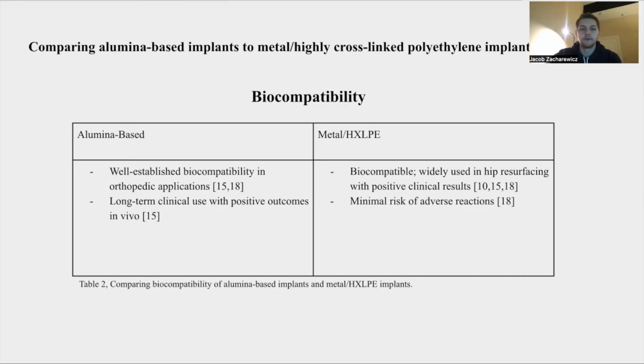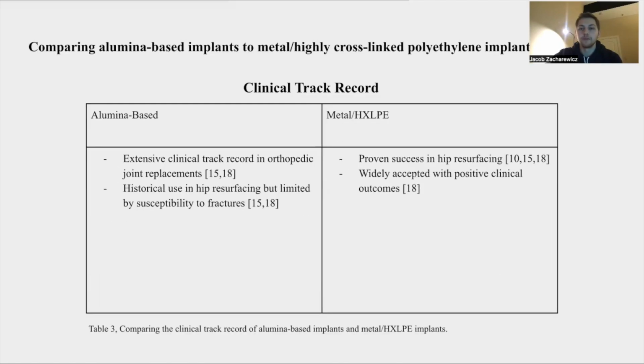Comparing the biocompatibility of alumina-based implants to metal and highly cross-linked polyethylene, both have been proven to be biocompatible with minimal risks. However, alumina has the ability to shatter, and once it does shatter, it is very hard, almost impossible, to pick up the debris surgically, which is a main reason why it has not been popular in the use of hip resurfacing. Alumina-based implants and metal and highly cross-linked polyethylene implants both have a very well-established clinical track record. However, the track record for metal and highly cross-linked polyethylene is much higher and much more favorable in hip resurfacing compared to that of alumina-based ceramics.